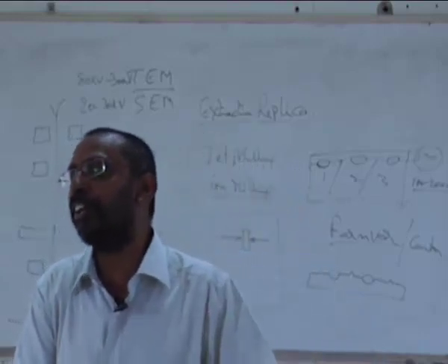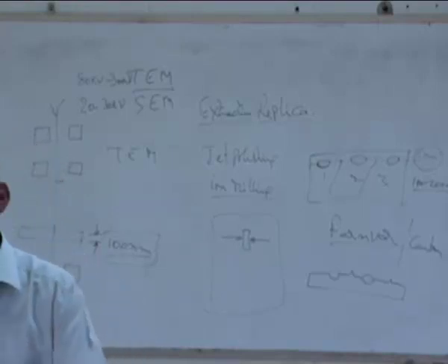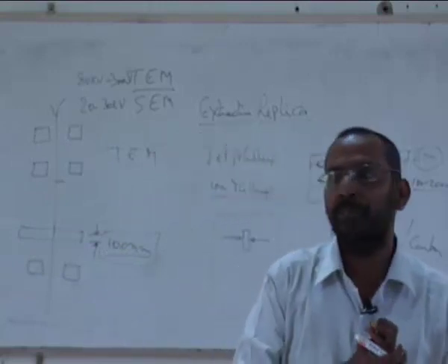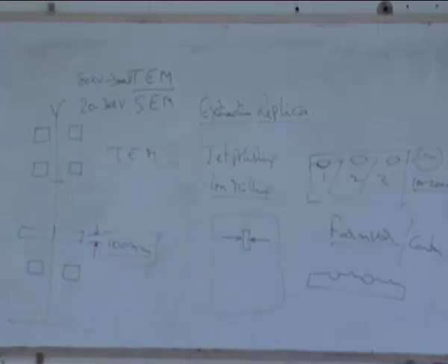There is a name for it, and there is a definite crystal structure for it, and there is a definite stoichiometry for it. It is not cementite. Cementite is the one which comes out at a much higher temperature when you are tempering the martensite, because that particular carbide which is coming out first gets converted into cementite later. And what is that first carbide? It's called epsilon carbide. Has anybody heard of epsilon carbide?